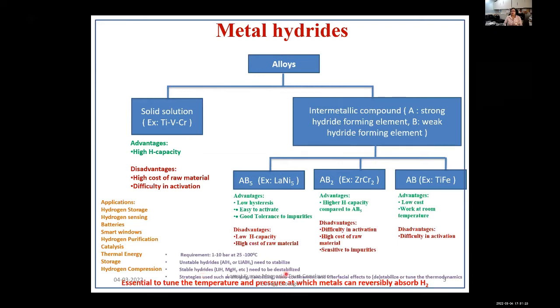So you have to make them destabilized. Now there are several strategies which could be followed in order to do that. Either you reduce the particle size, nano size it, do nano confinement, or you can alloy these, make several alloys, add certain additives, or generate certain defects so that the diffusion of hydrogen gets easier. All these can be done in order to either stabilize or destabilize these hydrides and tune their thermodynamics.